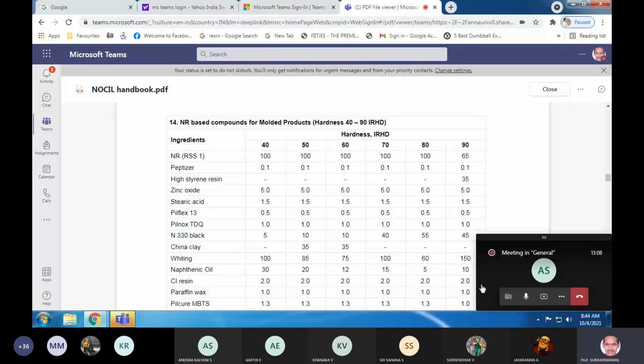One cross-linker for every 100 to 400 monomers. You can visualize the remaining unsaturation is still available. So this unsaturation can promote oxidation and ozone cracking. Why do we leave the unsaturation? Is it for the functionality? No. We want to leave a certain part of the rubber uncross-linked so that it imparts flexibility and resilience.